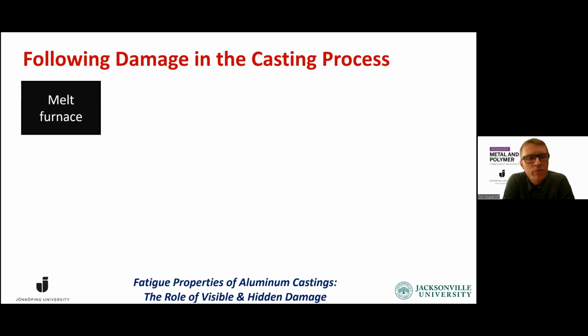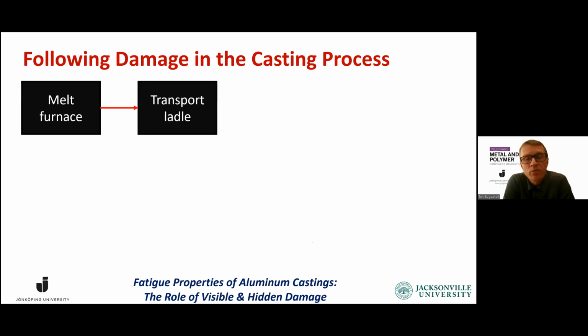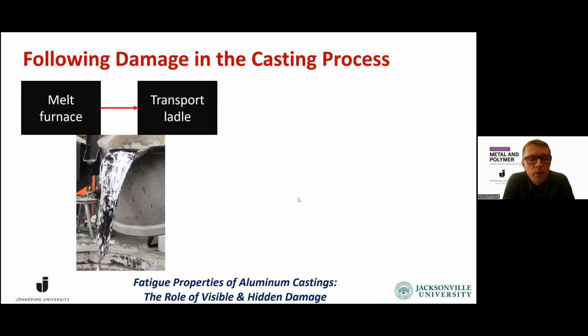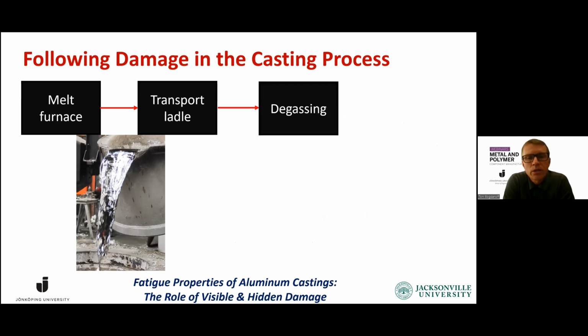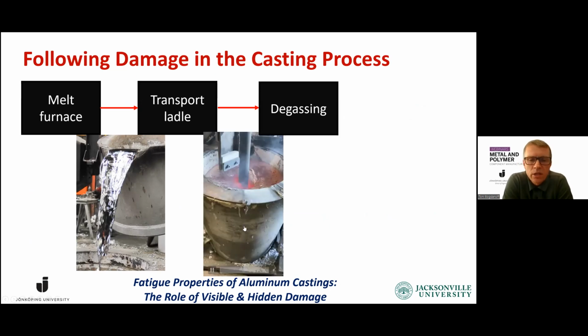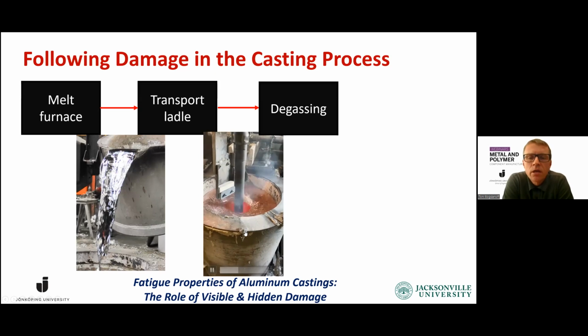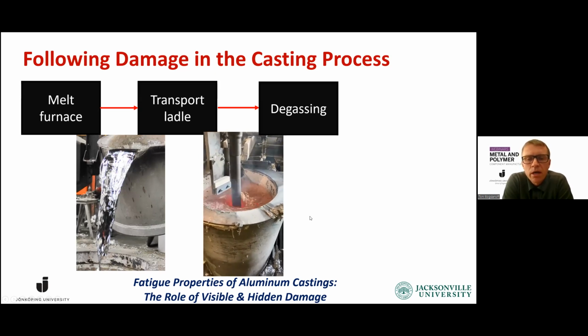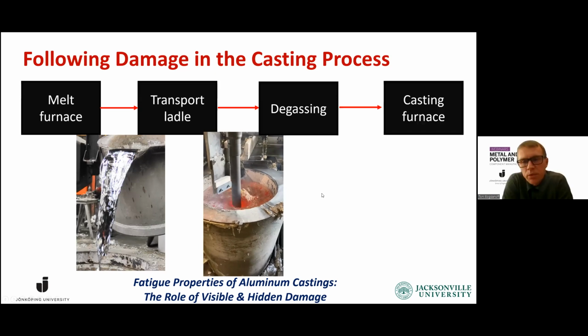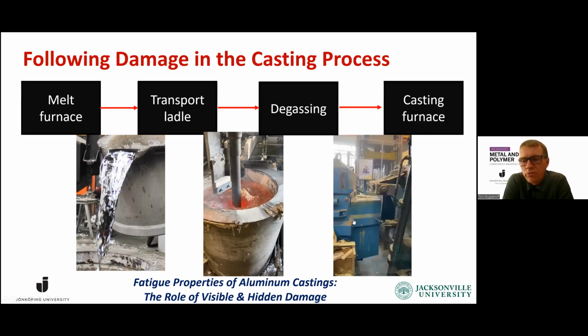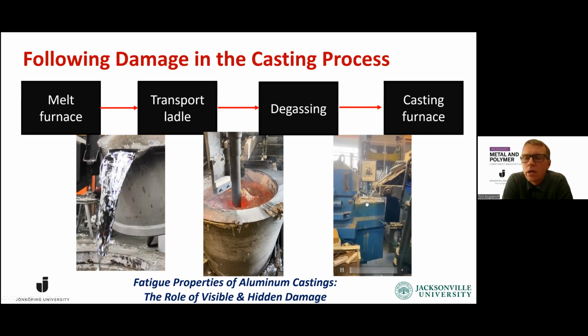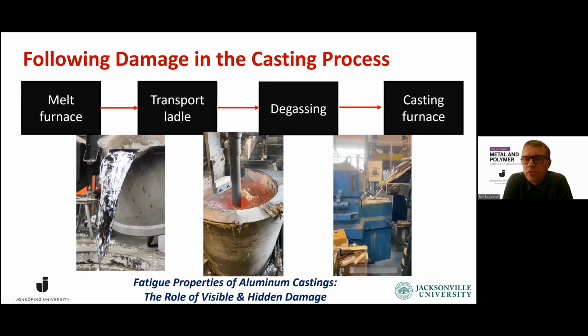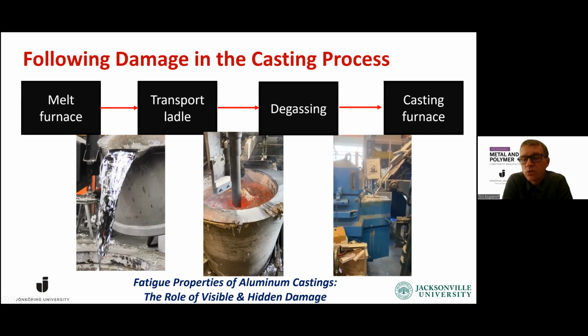So what we know is that we have a melt furnace where we melt, and then we have to get the melt somehow to the transport ladle, and that is by pouring, and we do it like water. And when we look at the quality, we continue with this fantastic step of degassing that we can see in this video, where we actually see one more time this big vortex dragging the surface down into the melt and creating more damage. The next step is that we have to pour it into the casting furnace, where we do another step of this. You see a violent flow, just filling the furnace as fast as possible to get the melt into the furnace in as short a time as possible.